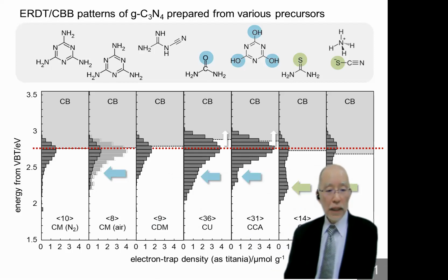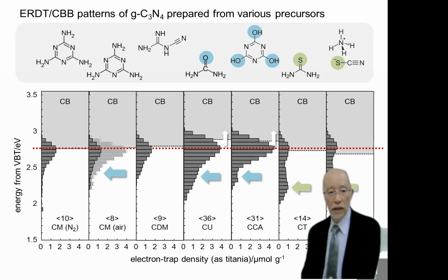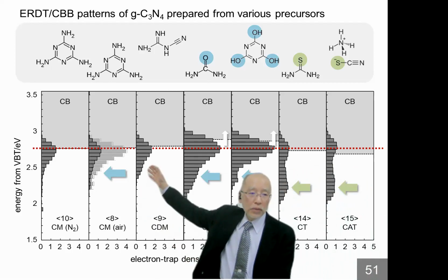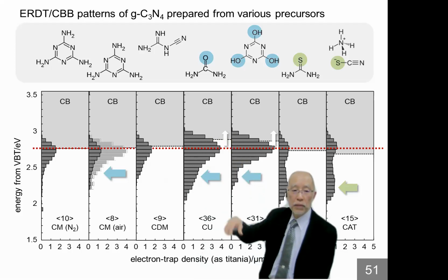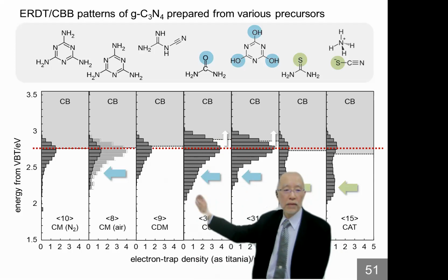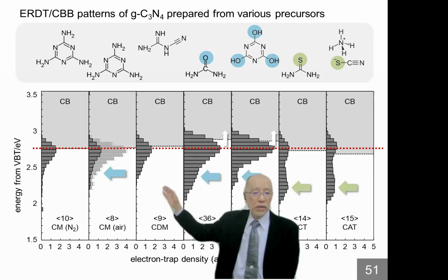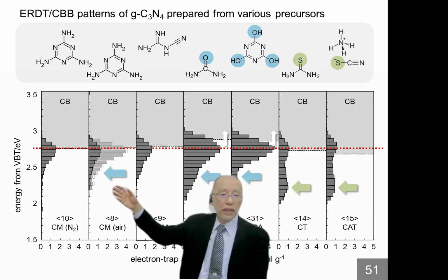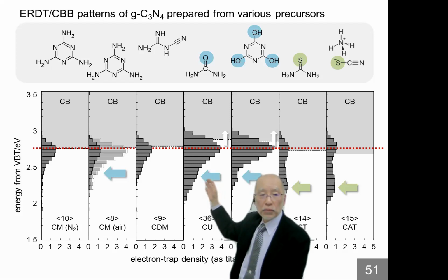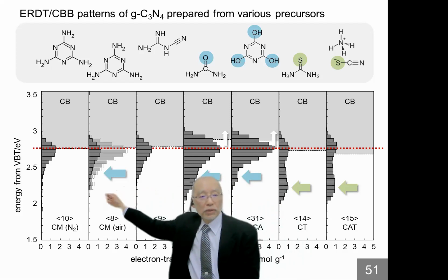But by measuring the ERDT/CBB pattern, that is very clear. If the ordinary starting material contains only C and N, that gives the peak around 2.8 electron volt. But if the precursor contains oxygen, then probably the surface or part of the bulk is doped with oxygen. That gives the lower energy side peaks here. That is very clear. And also, if this carbon nitride is prepared in nitrogen and heated in air, or prepared in air, a small tailing appears at the lower energy side, similar to that prepared with an oxygen-containing precursor. The tailing appeared here. So probably this part reflects the surface doping with oxygen.